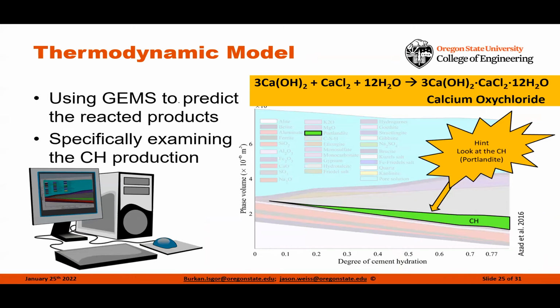So the chemical reaction that's taking place is referred to as calcium oxychloride. It's the calcium hydroxide in the system, plus the deicing salt, plus the water. It forms an expansive agent. This expansive agent expands upon cooling. And we can essentially have a really good prediction of this if we simply know how much calcium hydroxide there is in our particular mixture.